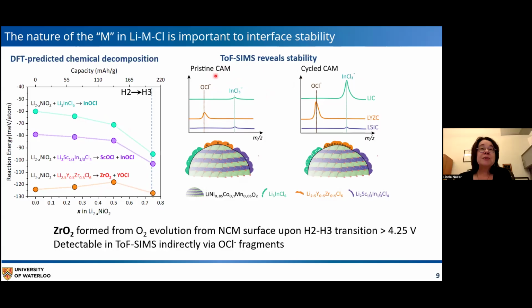But if we compare the pristine cathode active material with the cycled, you can see in the case of the LYZC, there is a strong indication of formation of oxychloride. We see a little of that at the start just because of some moisture in the chamber, but that intensity increases on cycling. And this is the characteristic feature of this reaction. We can't actually see the zirconium in the case of TOF-SIMS because it's not very sensitive. So we detect the formation of the zirconium via the formation of the oxychloride.